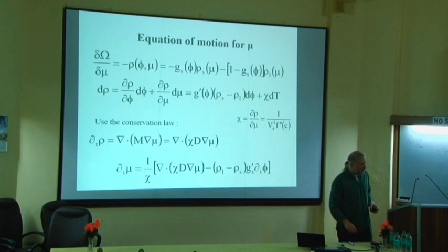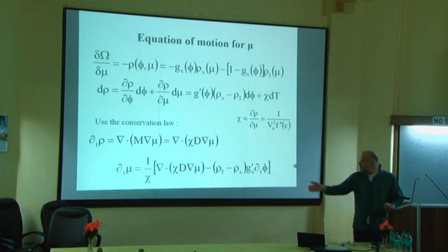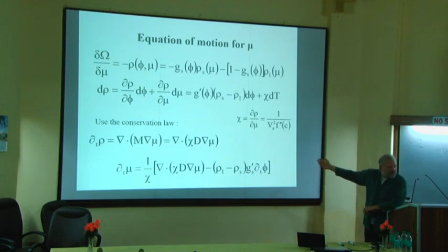Now, there is one problem. This is an equation that works perfectly well for arbitrary free energy. So you can take a Calphad free energy, and you can go through everything. Generally, you cannot do that analytically, but well, that's why we have computers. So the equation is set up, the recipe is there, and it works, right?